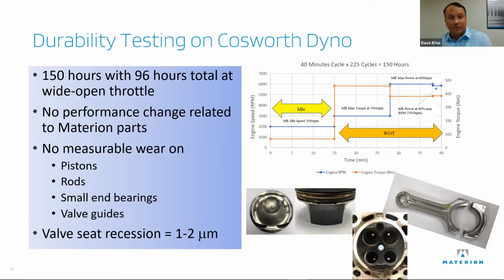So that results in 150 hours, 96 at wide open throttle, and absolutely no performance changes were seen related to the Materion parts. They blew the head gasket twice, so it shows you they were running the engine pretty strong. And there was no measurable wear on any of the parts. They expected that from knowing what they know about the pistons and the Performat for the seats and guides. The Tough Met rod was a surprise to them. Actually, no problems at all with it. And the valve seat recession was so minimal, it was a little bit of 1 to 2 microns of increase in valve lash. That was about it.